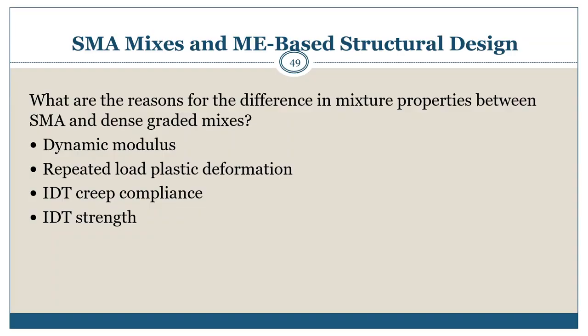However, in reality, mixes are confined as placed on the roadway. So the interparticle friction of SMA mixes does become a benefit, and the stiffnesses are equal or greater than the dense graded mixes, resulting in lower rut depths. Repeated load plastic deformation values are lower than the values measured for conventional dense graded mixes because the test procedure includes confinement. So the test results exhibit the impact of higher internal friction of SMA mixtures. In other words, more resistant to plastic deformation, which means lower rutting.